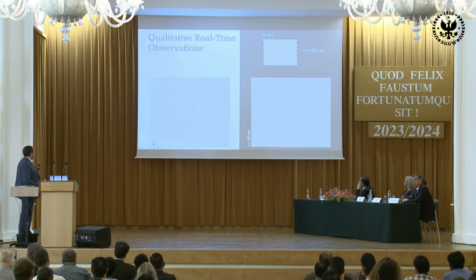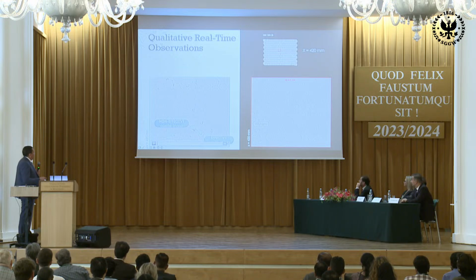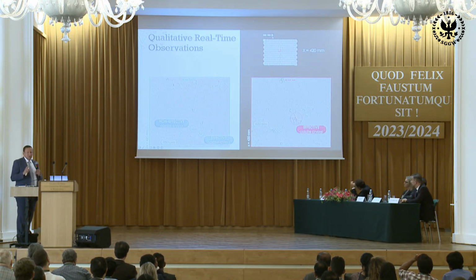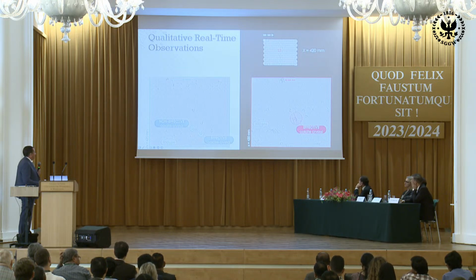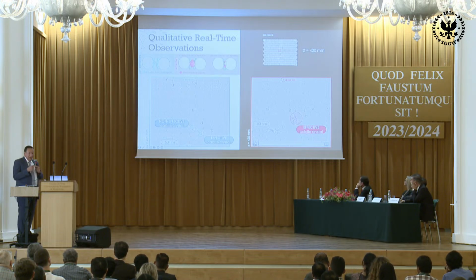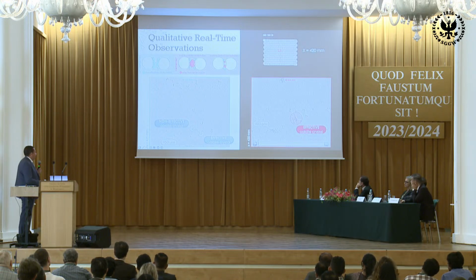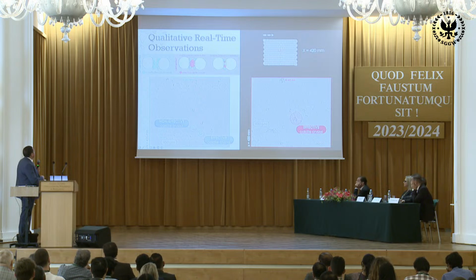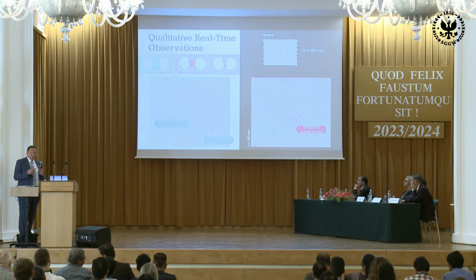In this first case of uniformly distributed pores, we see first that we have two kinds of contact. Some of them make contact between two grains and others just cover the grains. We see it better in a heterogeneous case, and here you have the time running, so the whole process is happening in 24 hours maximum. Here we see it better. We have what we defined as two groups: the effective crystals that really create glue between the grains, like this one, and those, like this one, that cover the grains but are not creating glue. So they change the porosity, but not the cohesion.